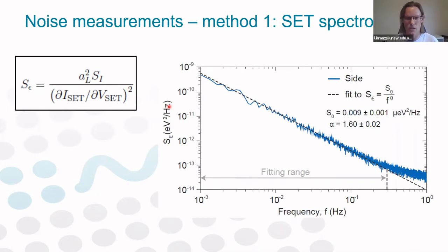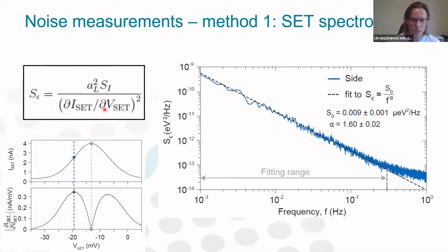And actually what I'm showing here now is the fluctuations in the electrochemical potential. So the units of these fluctuations are now in absolute energy scales, and the translation between the fluctuations in current that I showed on the previous slide and the fluctuations in electrochemical potential that I'm showing on this slide is given by this equation. So maybe I can explain this quickly. First of all, you need to consider how much the change in current is caused by changing, for example, a voltage using your control gate. So you have to consider this factor, the dI/dV. On the other hand, you also need to take into account the lever arm, which converts the voltage fluctuations into absolute energy scale.